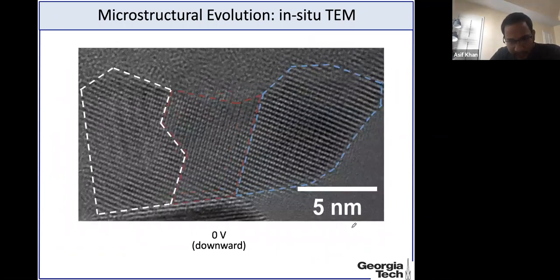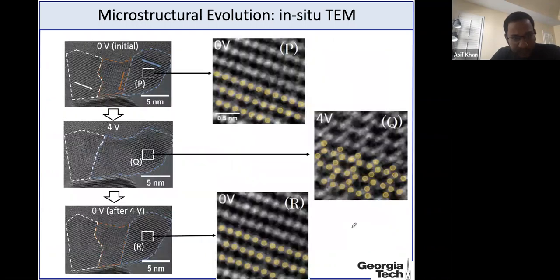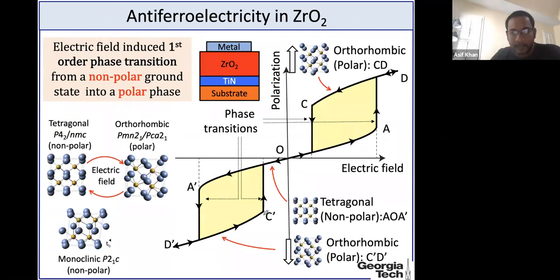So in the interest of time, I will just focus on one thing over here. One of the interesting things that we saw is that when we look at a certain region of this domain here, we see that there is a line of atoms over here. When we apply 4 volts across it, we see another line appearing over here. So initially we have this line of atoms, then a second line of atoms appears. And then when we go back to 0 volt, this line of atoms disappears. So that was a pretty interesting thing that we saw.